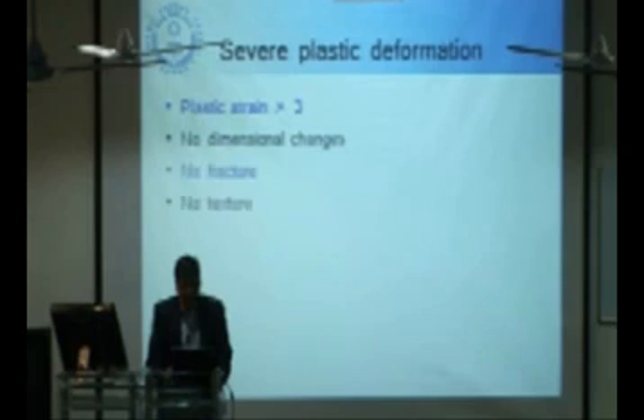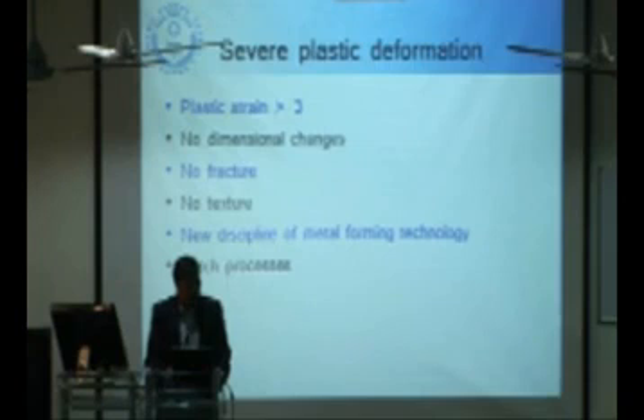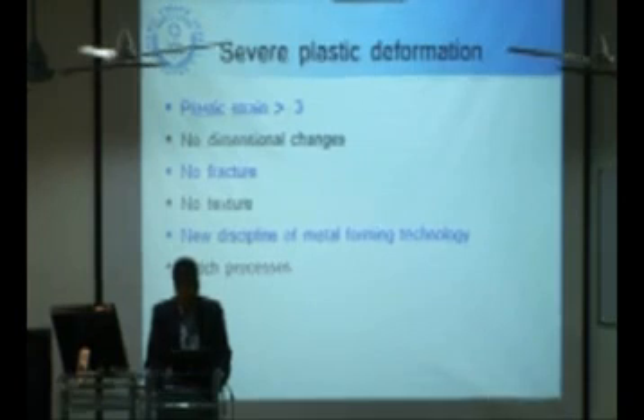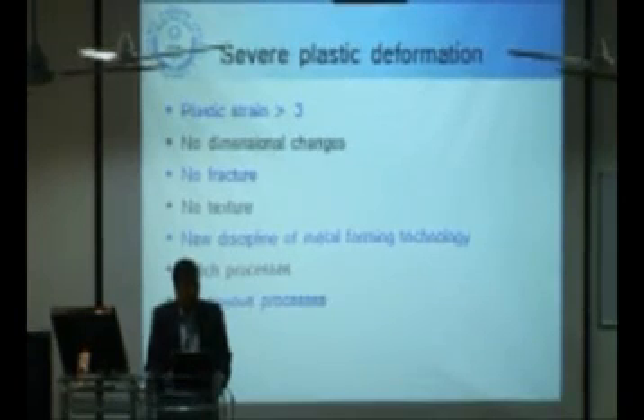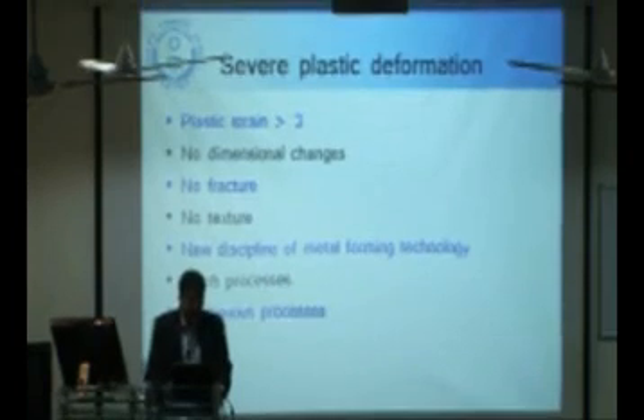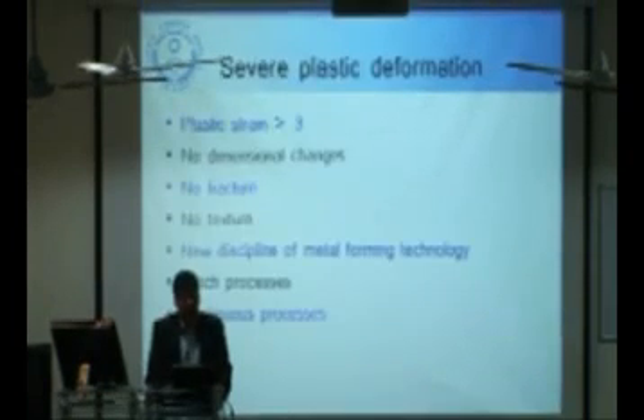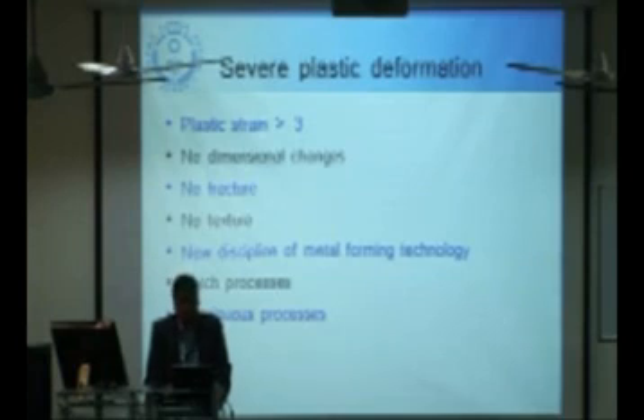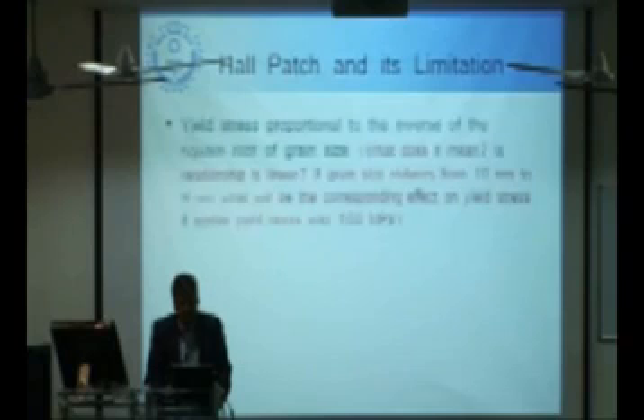What we can achieve by severe plastic deformation is a plastic strain of the order of greater than 3, no dimensional changes, no fracture, no texture, a new discipline of metal forming technology. But right now it is a batch process. And what we are aiming at is to develop a continuous process in which we can apply this severe plastic deformation. This entire work is based on the Hall-Petch relationship, which states that if we are able to minimize the grain size, there will be an increase in the yield stress.